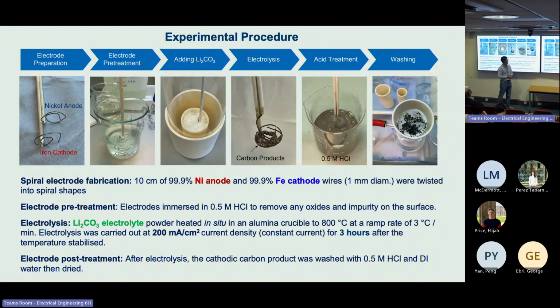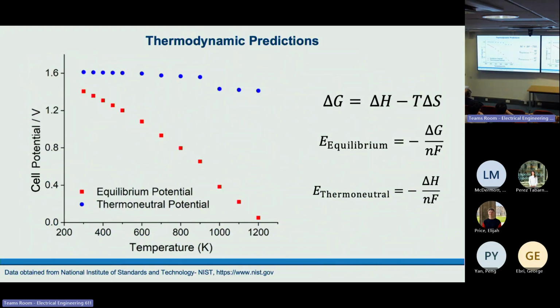We use suction filtration then to filter the suspension to get the carbon products and dry it under the airflow. So here we did some thermodynamics prediction using the data we obtained from NIST. At around 800 degrees, the thermal neutral potential is around 1.5 volts.